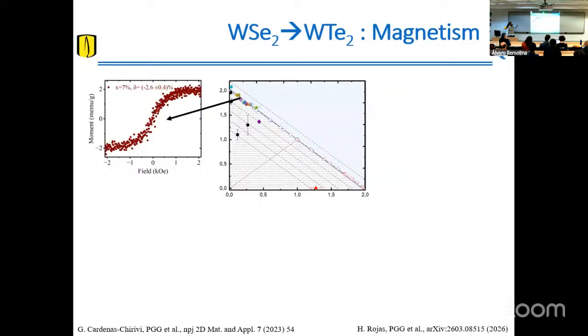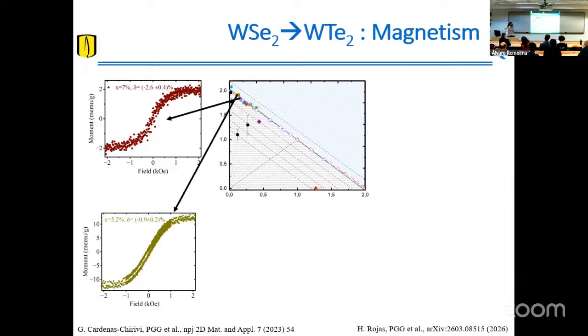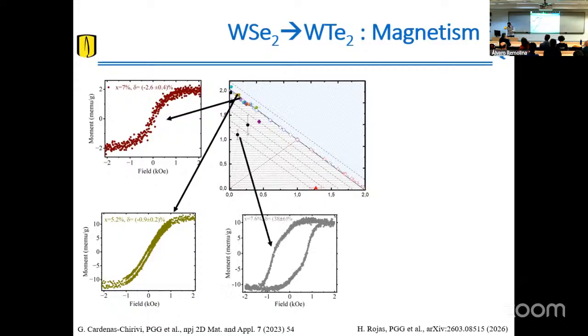So we see that with a low number of defects, we have paramagnetic states, and the paramagnetic state starts to develop into a little hysteresis that speaks of ferromagnetism. And then we have big hysteresis loops, which talk about the strengthening of this ferromagnetism for the region of the phase diagram in which we have lots of vacancies in the system. So we characterize this magnetic phase by the coercive field. This is the field at which we can switch the magnetization direction.